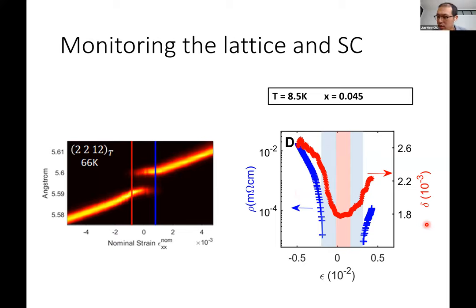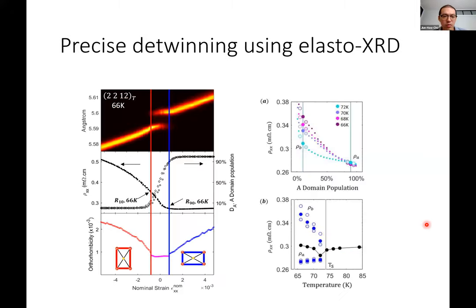So in addition to measuring this superconducting and lattice response, we are now also doing some measurements we did a very long time ago, but now in a more precise fashion, which is detwinning the crystal and then measuring the spontaneous resistivity anisotropy.